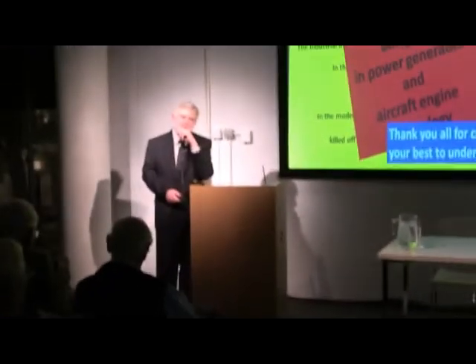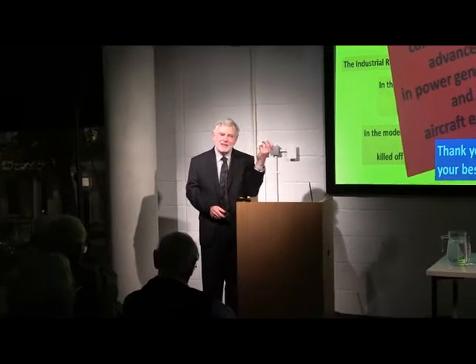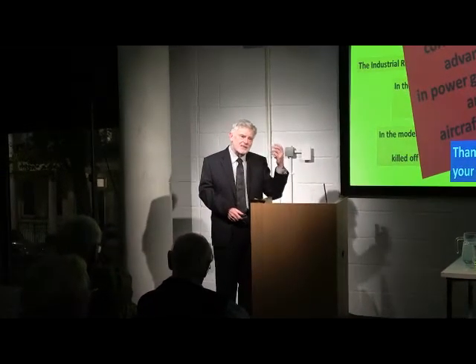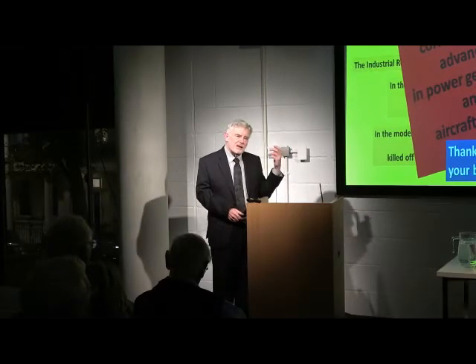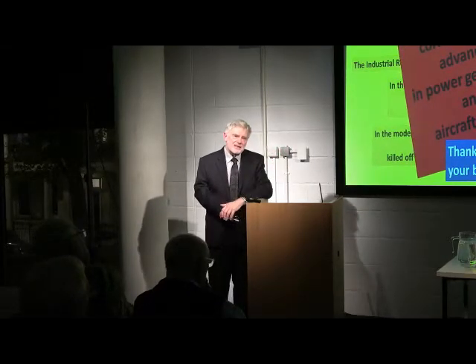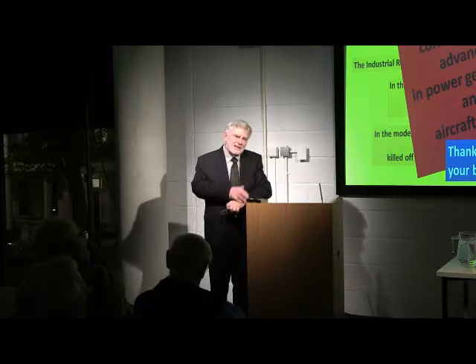And the other thing we did is, for ultra-high vacuums, we used a thing called a getter ion pump. What that did is it ionized the residual gas, accelerated it, and slammed it into a sheet of titanium. I think they still use getter ion pumps to get high vacuums, so titanium is really good at absorbing oxygen molecules and ions at very low pressure. Well, that's a bit like what I was just telling you about in terms of the spacecraft. You're doing something which effectively gives the oxygen atom a lot of energy to react with the titanium. I've not heard of exactly how that was done.